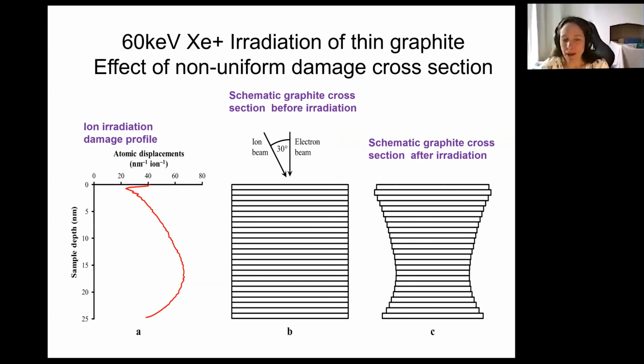Okay, so why is this happening? Well, let's look in a little bit more detail at what the ion irradiation is doing to the specimen. The ion implantation depth causes more shrinkage at a depth of about 15, 18 nanometers than it does at the surface and at the bottom of the specimen. And that is reflected in a difference in the shrinkage. So if you start off with a material that is a perfect slab, then the shrinkage due to the Gaussian implantation peak that you'd expect to see is demonstrated by this crystal here. And that might well be what would happen for an amorphous system.